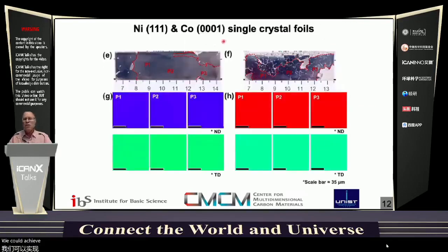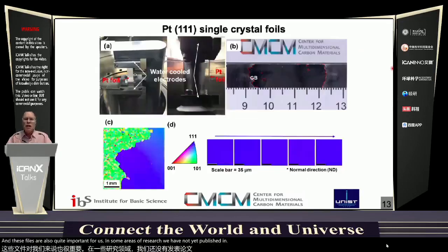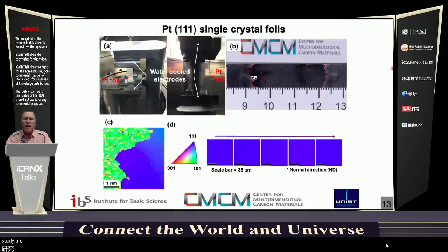We could achieve a similar sort of thing. Copper seems to work a little bit better, but we also achieved this with nickel and cobalt, obtaining the FCC 111 close packed or 0001 HCP close packed planes. And the EBSD patterns again show the same out of plane and in plane orientation. You can, however, see evidence of twinning, particularly with the cobalt. And these foils are also quite important for us in some areas of research we have not yet published in. And then it was possible to also study platinum and palladium.